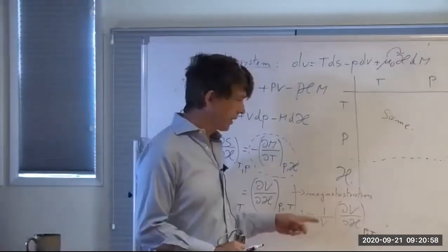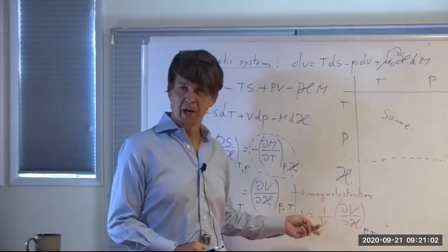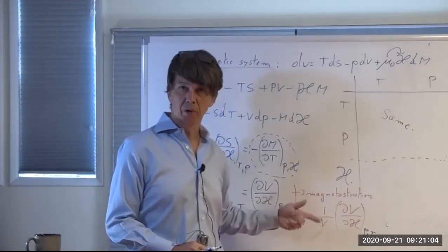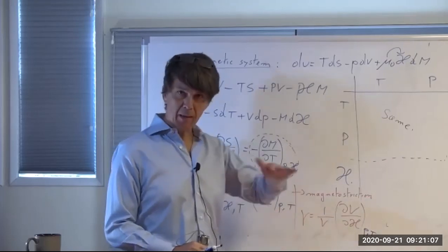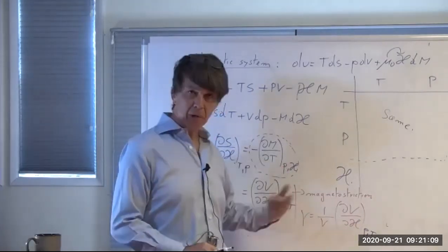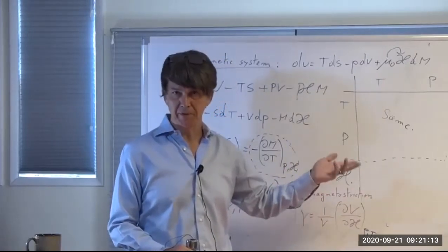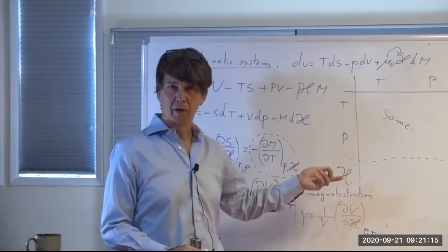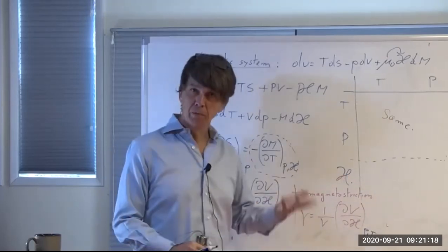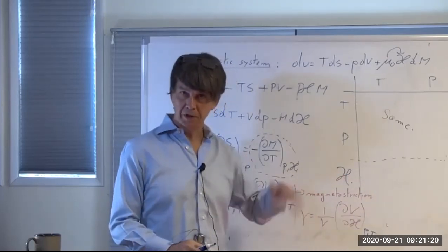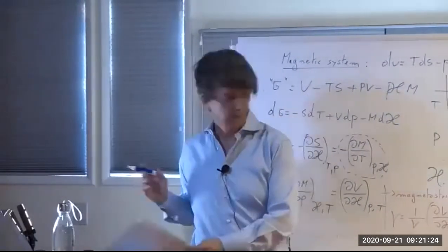By the way, this is one reason that transformers hum, right? Because when I apply a magnetic field to the iron core, which is a bunch of lamella, right? When I apply a field, remember in a transformer, the field is switching at 50 or 60, whatever frequency you're on, times per second, the volume slightly changes. So this is actually what causes hum. Okay, I'm running out of space here.